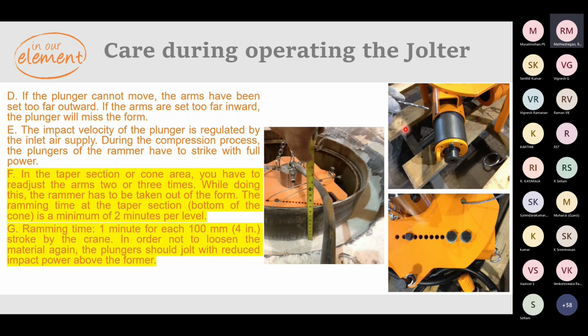In the taper section, ensure the distance between the former and plunger is adjusted properly, and run the vibrator for 2 minutes per level, because normally this is uplifted by the crane. So at each level you have to do 2 minutes. For the sidewall, vibrate for 1 minute for each 100 mm thickness. Set the level and the vibration speed accordingly, to avoid disturbing the material which has already been compacted.